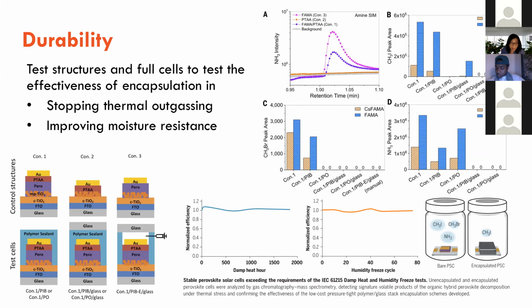We want to accelerate test them, meaning that we don't have 25 years to wait for a perovskite cell to last. We want to see if they can withstand high cycles of torturing and long hours of damp and heat environment. So these comply with the IEC standards that are used for the current photovoltaic products. So we can see that this encapsulation strategy that we propose is working extremely well. This is actually the record durability of perovskite cells ever reported.